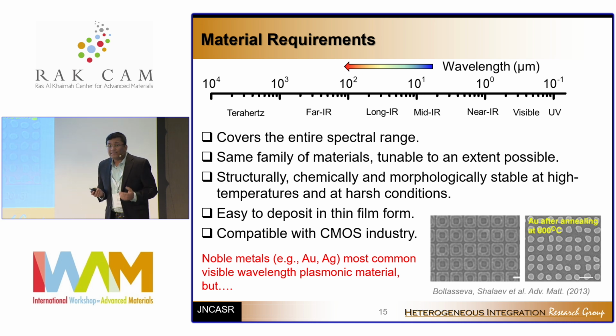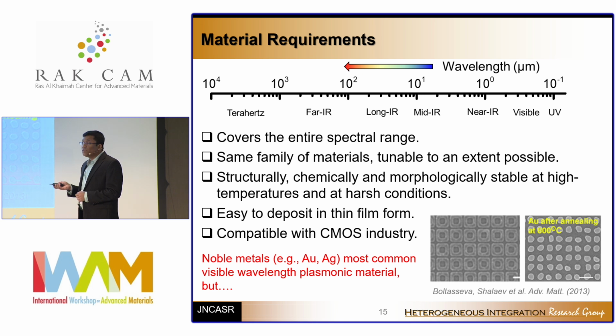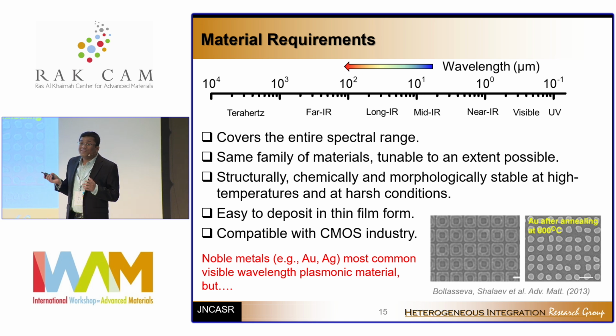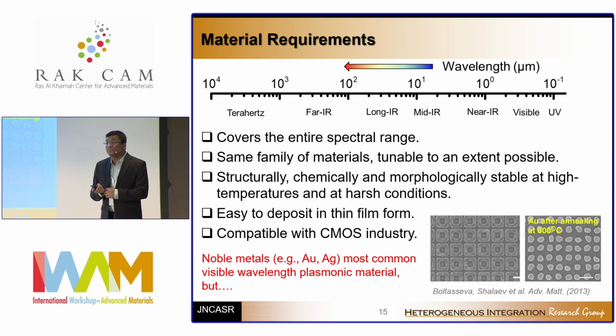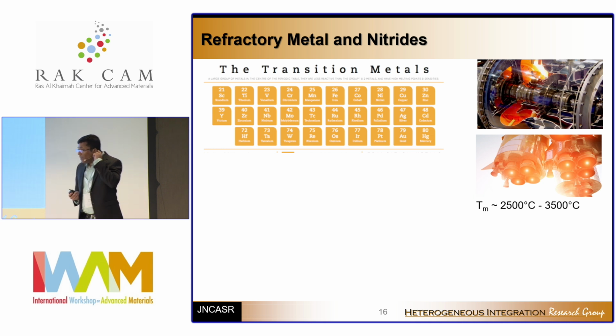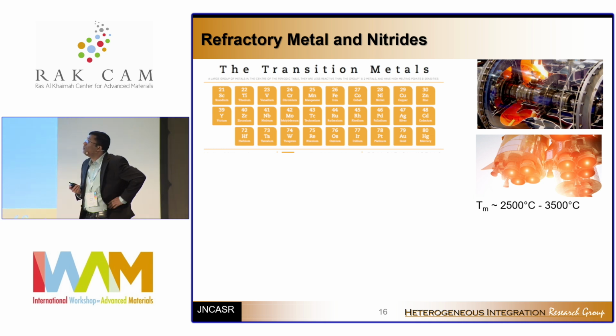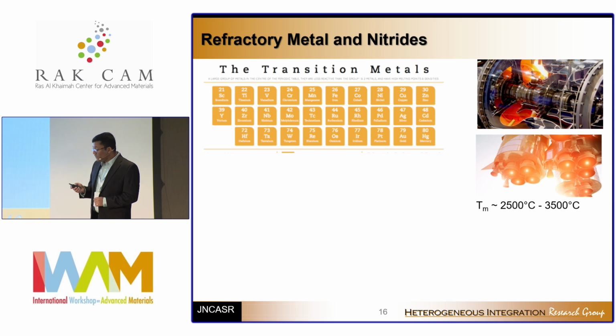And that's exactly the reason why, while there is absolutely no doubt that gold and silver are the best plasmonic materials in the world, you really can't use them for practical application because they are not stable, you cannot deposit them in the thin film phase, and so on and so forth. So that's where we come in, and what we research is transition metals and transition metal nitrides.